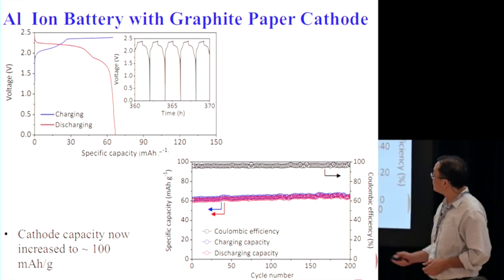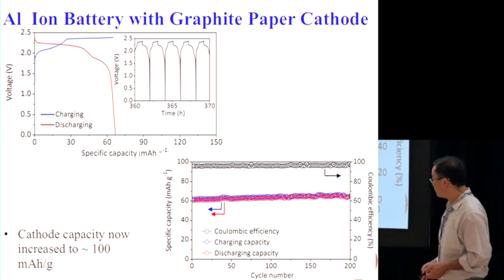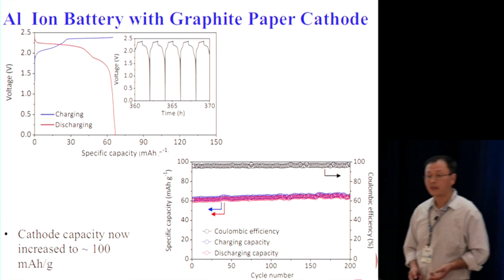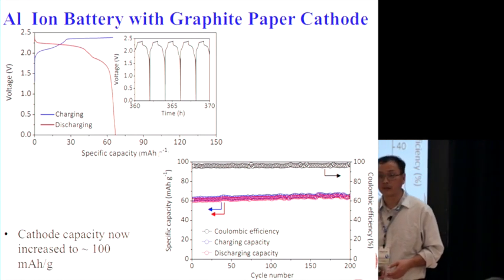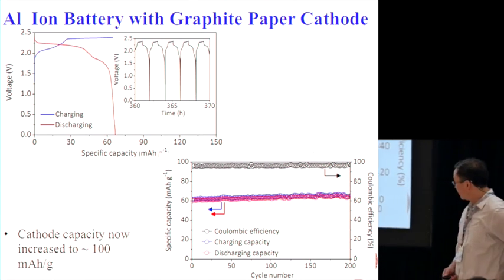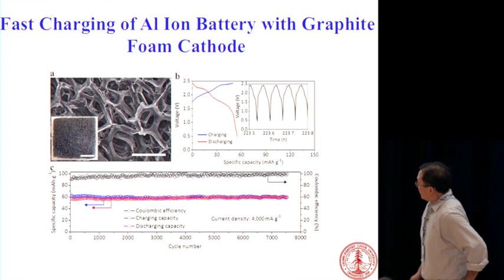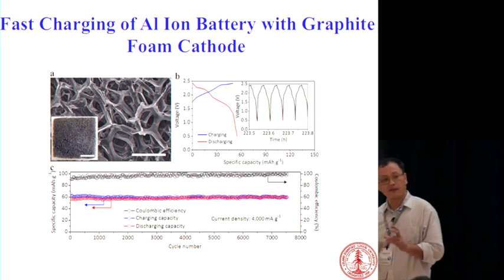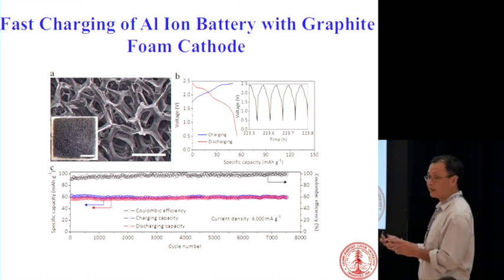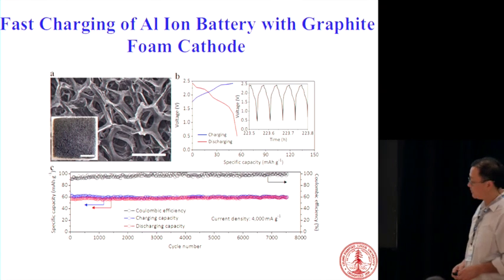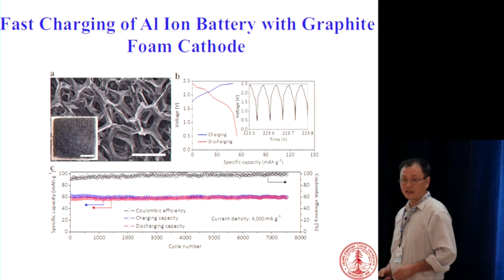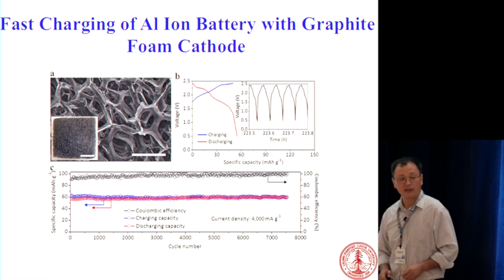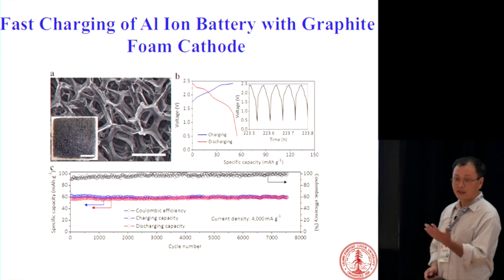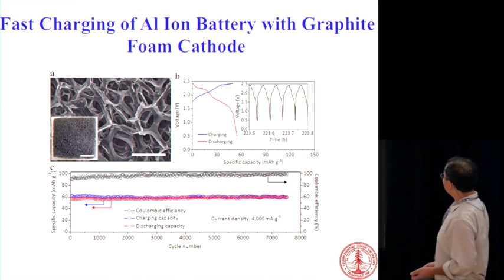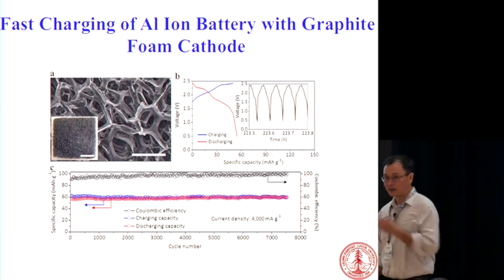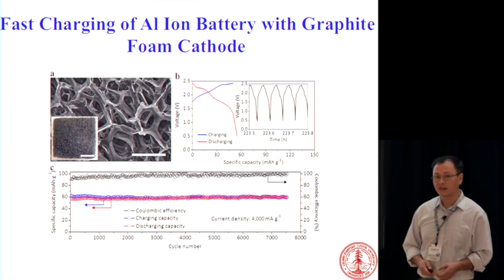And the cathode capacity was low, was about 60-some milliamp hour per gram, and now it's up to about 100 milliamp hour per gram. Okay, by engineering the right graphite material, we're able to increase the energy density of this battery. And what's also interesting is that if you make the graphite side porous, okay, like in this case, we have these porous graphitic whiskers in the electrode, you can charge and discharge very quickly. Okay, so this is a very high current charging, and we can charge and discharge less than a minute, okay, to get this battery to go. And the paper, the cycle life here is about 7,000 cycles, but now we have much longer data.